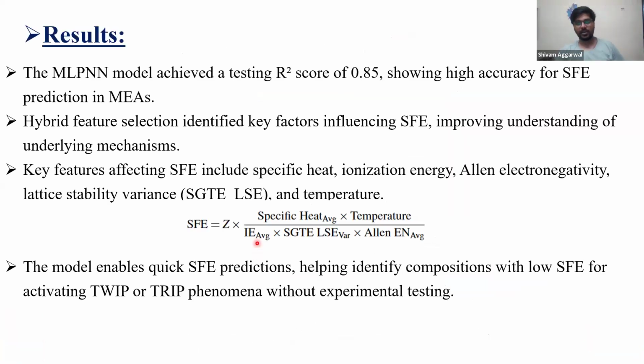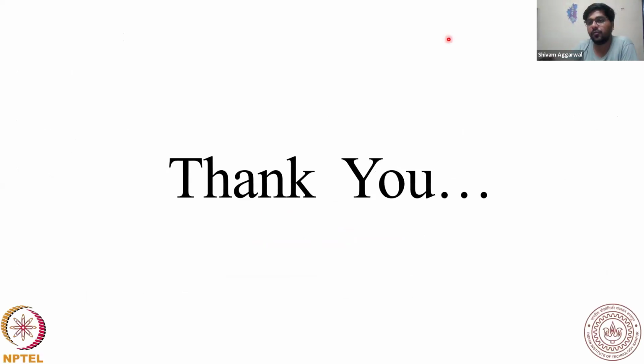So these are some results. They got a very good R2 score value of 0.85 for the train test set, and they identified some features which highly influence the stacking fault energy. They also got a kind of empirical formula for the stacking fault energy using these input properties. And they enabled quick SFE prediction to identify low SFE for activating any phenomena which they require, without experimental testing. Thank you so much for hearing me. If you have any question, please feel free to ask.